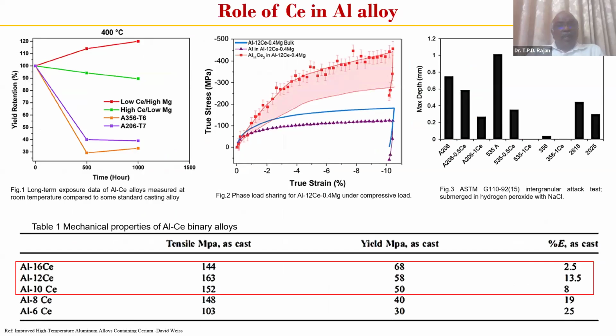For example, the strength of pure aluminum is around 60 to 70 megapascal. But when you add cerium to it, the tensile property increases to a higher extent. For example, 10 cerium has 152 and 12 cerium has 163 and so on. Similarly, the yield strength also increases, but normally the percentage elongation will come down.